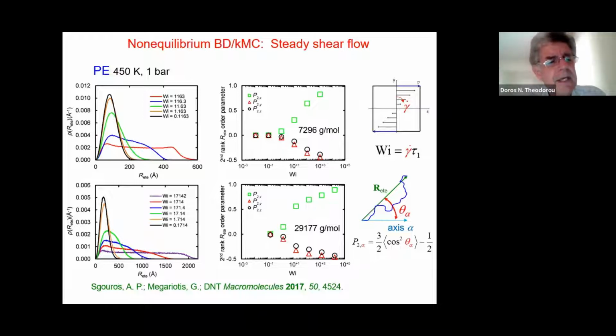So what we show here is the end-to-end distance distribution, the distribution of end-to-end distances of chains for two melts of polyethylene of roughly 7,300 and 30,000 grams per mole molecular weight for a variety of Weissenberg numbers. And one can see that when the Weissenberg number, which again is this dimensionless shear rate, is low, below 1, for example, the chains assume conformations which are typical of equilibrium, essentially Gaussian conformations. However, when the flow is very strong, when the Weissenberg number is very large, then the chains are unraveled by the flow, and this end-to-end distance distribution becomes very broad. You have some very extended chains in the system.